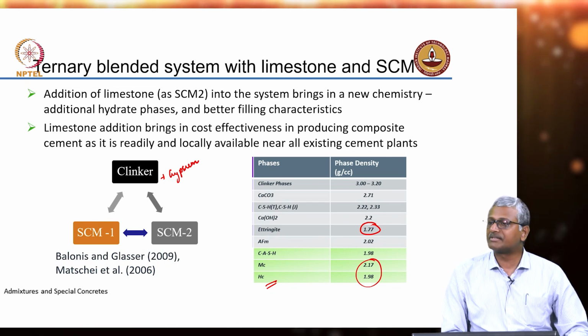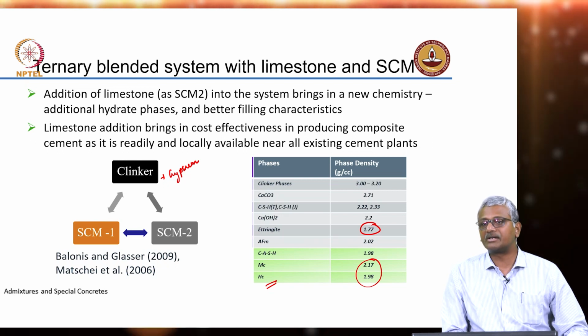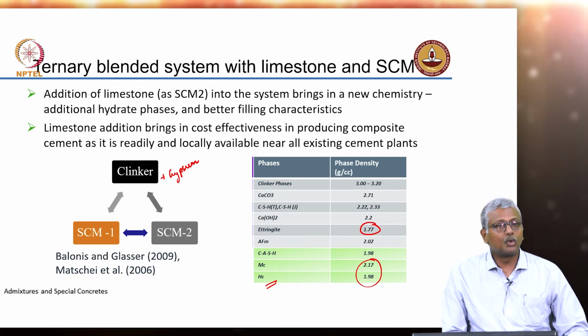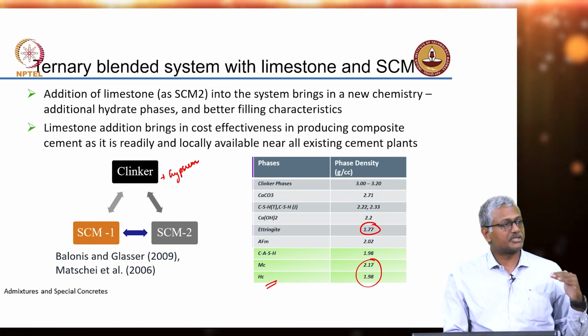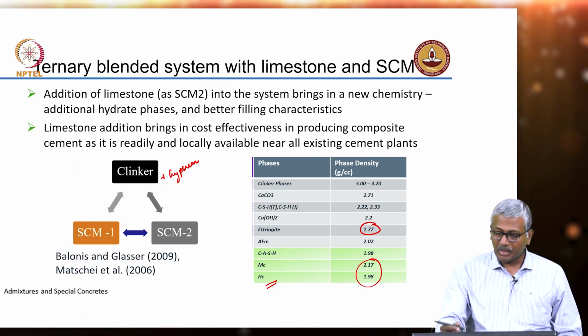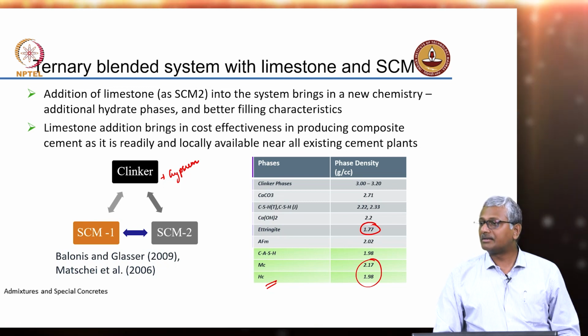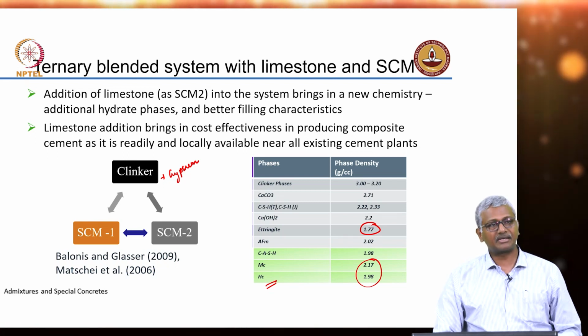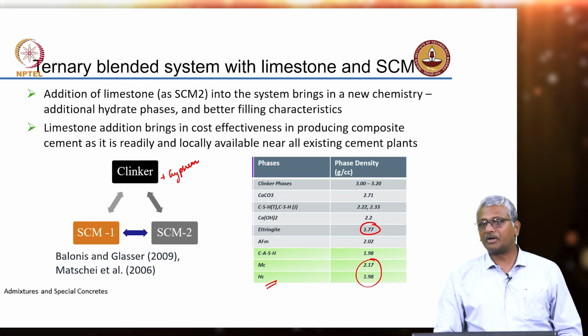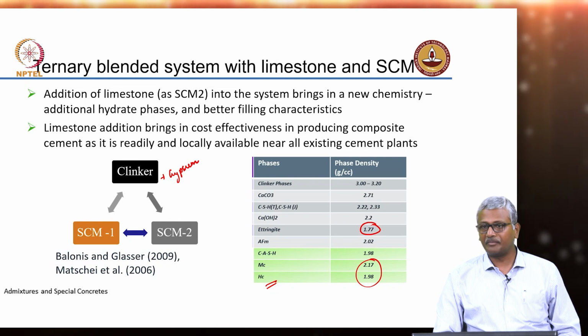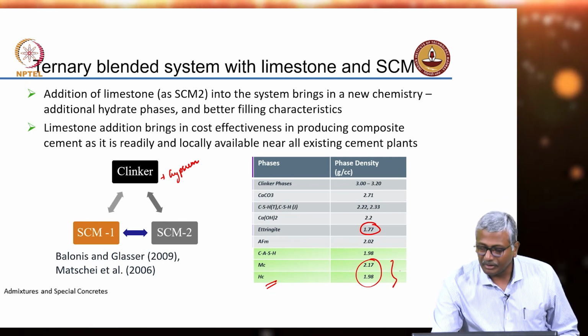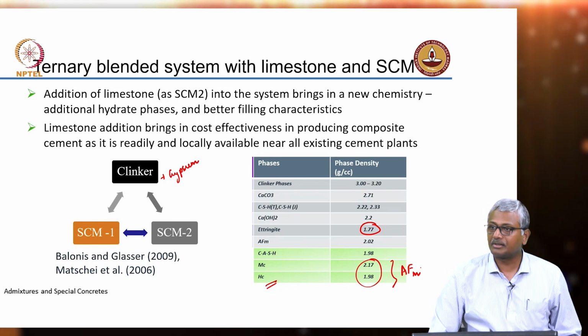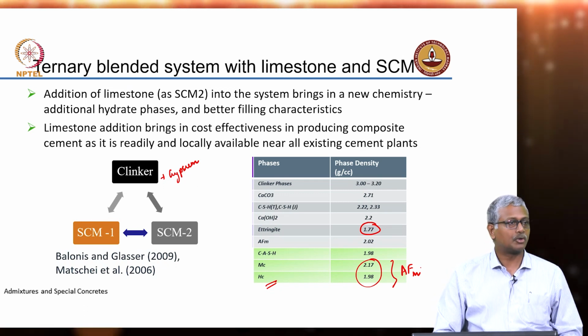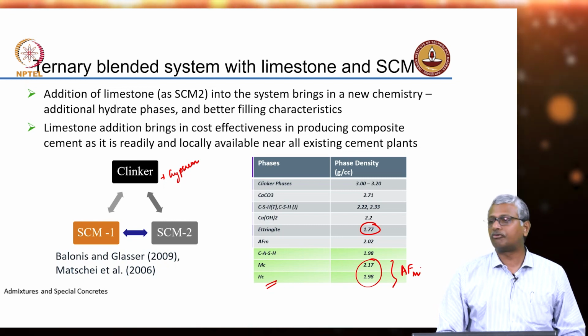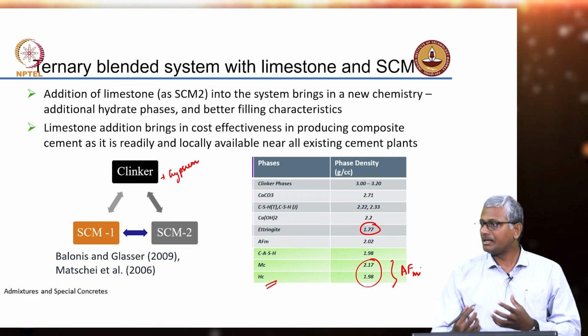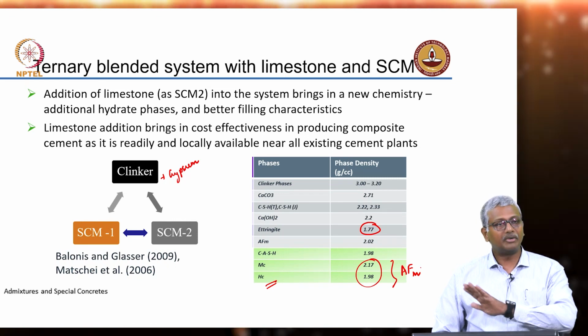And if you remember, we discussed the fact that sulfate resistant cement systems are designed from the perspective of low C3A, so that ettringite that forms at early stages remains stable. So when you have such a system, the stability of ettringite is ensured, and this ettringite will remain stable for a long period of time and not really decompose to AFm. AFm formation is going to reduce because you are forming other AFm phases in terms of carbonates. You are not forming monosulfate anymore, you are forming monocarbonate, but you are still taking care of the alumina. So the ettringite that is already formed remains as such.